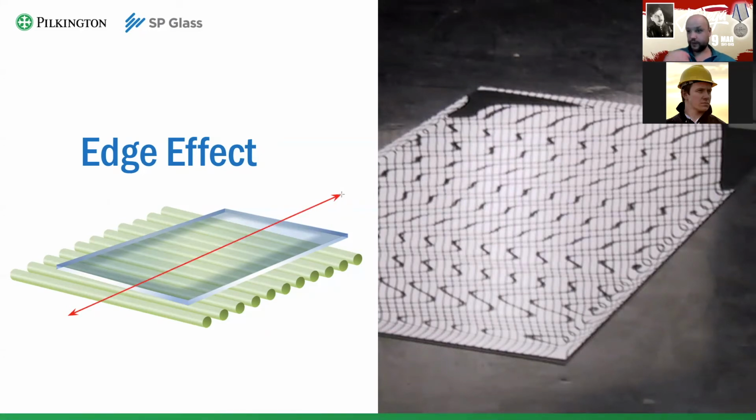If it takes heat from the rollers, the rollers become colder and the glass becomes hotter. And think of this, the front side here and the back side here, they are always moving on the hotter rollers, so they are always taking more heat. Also, edges of the glass are heated through the sides, so the glass edges are heated more than the central part.